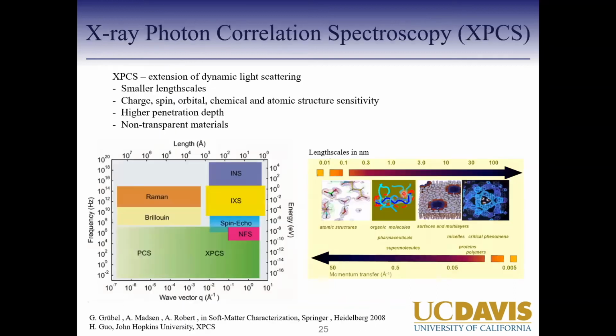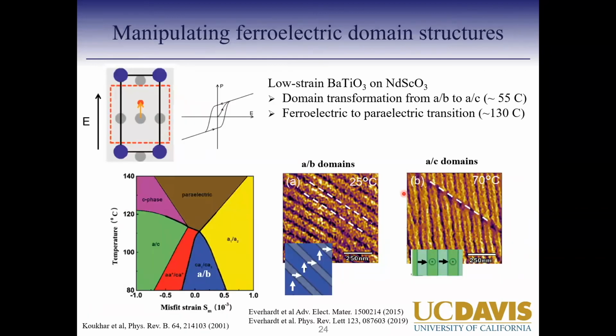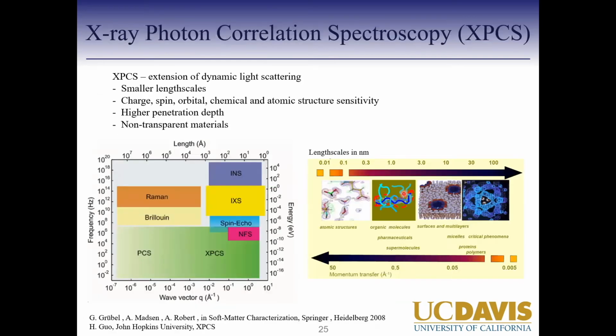We looked at these fluctuations, and the way to look at fluctuations in these domain structures is to utilize X-ray photon correlation spectroscopy. So you want to look at domains which are coming because of change in atomic structure. So you need very high sensitivity to the atomic structures, which is given by X-rays. And then we want to look at fluctuations and look at small length scales. So that's something we can use correlation spectroscopy technique to look at.